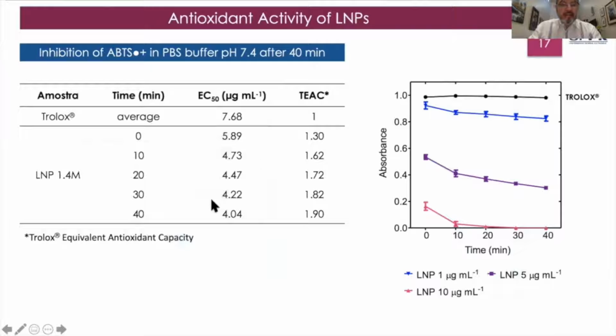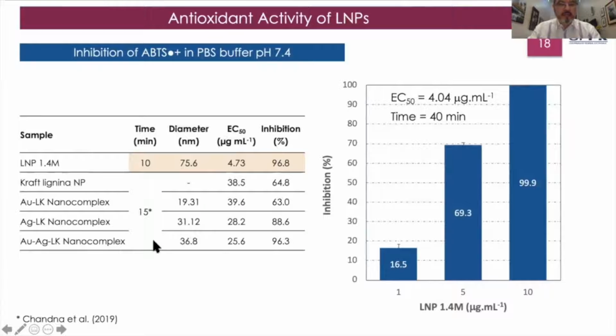Again, with the data coming from the calibration curve, one could calculate not only the EC50 values, but also the Trolox equivalent antioxidant capacity, TEAC. And it is clear that after 30 to 40 minutes, the highest levels of antioxidant activity of those particles were achieved. And that was probably due to the capacity of neutralizing radicals more efficiently due to the chemical groups and chemical properties altogether with the high surface area of those particles. Compared to other materials found in the literature, our lignin nanoparticles displayed a superior performance.